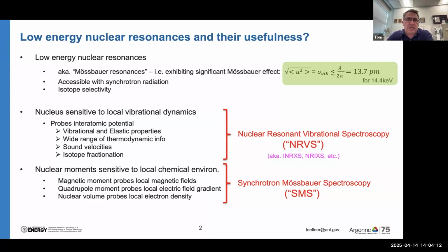Probing interatomic potential allows you to access vibrational and elastic properties of the material. It also allows one to extract the partial phonon density of states for the resonant atom, and this gives a wide range of thermodynamic information that is related to or derived from the density of states. Some of these are the sound velocity as well as isotope fractionation, which are popular in the geoscience community.